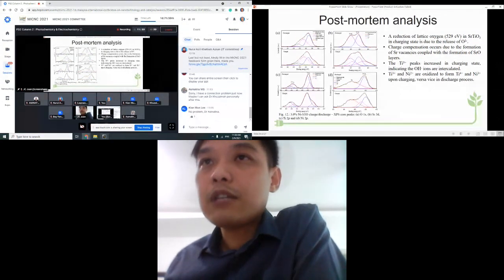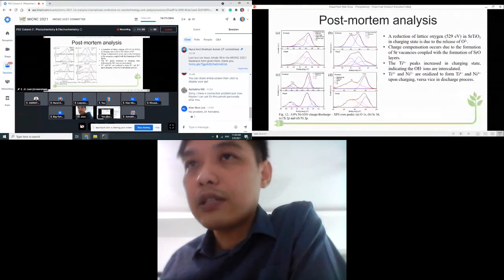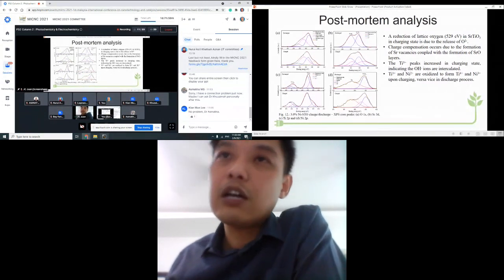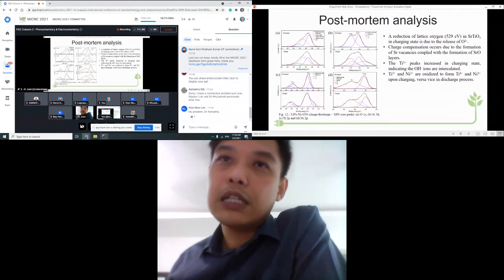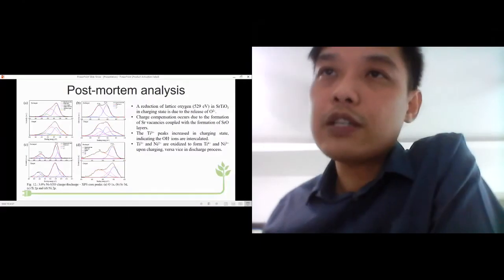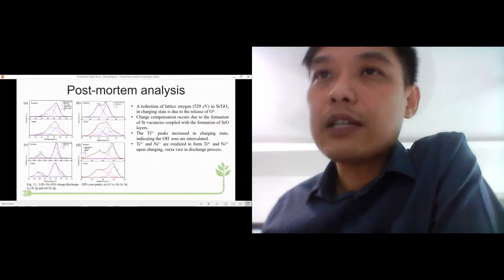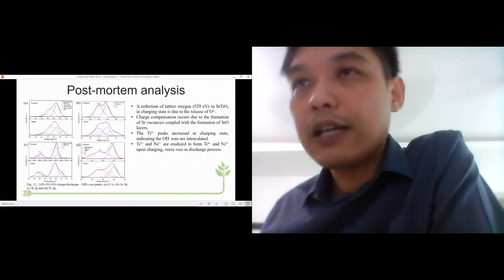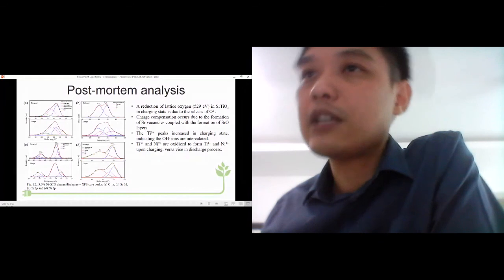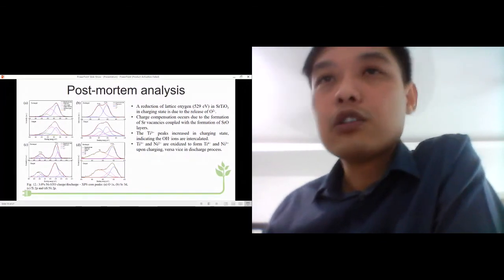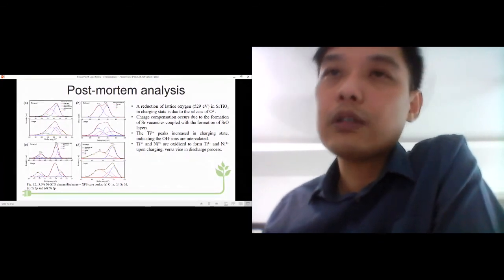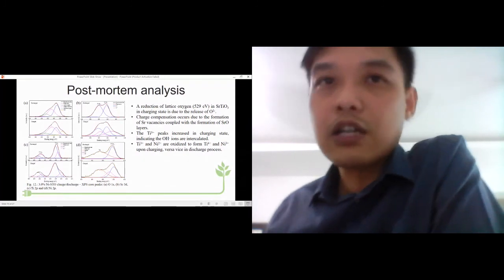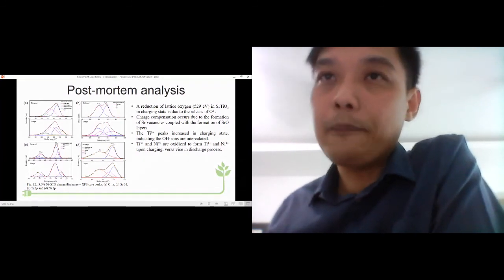And the Ti3+ peak increases in charging state, indicating OH ion is intercalated, as mentioned just now, to balance up the charge. The mechanism always involves this hydroxyl ion. Ti3+ and nickel 2+ are oxidized to form Ti4+ and nickel 3+ upon charging, and vice versa on discharge. So as mentioned just now, these charge discharge issues have been resolved. They can charge and discharge in a very stable form.